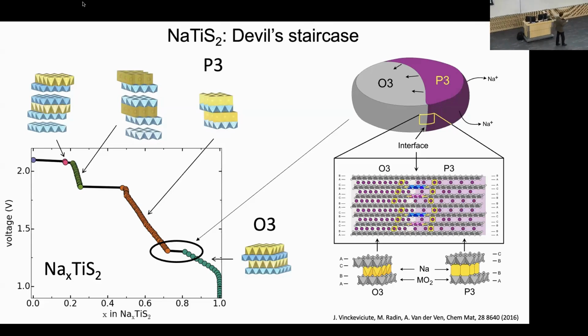It's a chemical driving force that causes dislocations to move through this crystal to realize this stacking sequence. So it's a very interesting chemomechanical problem that is still not really well understood. And there hasn't been much done experimentally to characterize this, because all this stuff happens dynamically. It's very difficult to kind of trap this type of structure. But there's a lot of fundamental science still to be developed and discovered there.